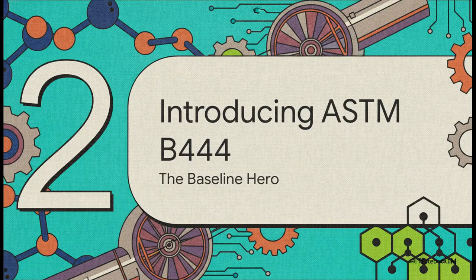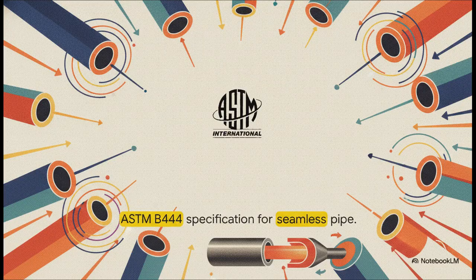Section 2. Introducing ASTM B444. This brings us to the baseline material that engineers turn to for these exact, unforgiving scenarios. The official ASTM International designation governs seamless pipe and tube, and that word, seamless, is absolutely critical here. It means the pipe is produced from solid billets by hot extrusion or piercing, and then it's followed by rolling and sizing. Because there's no longitudinal weld seam running down the pipe, the full wall thickness carries the pressure. Plus, there's no heat-affected zone from welding that could act as a weak point or a sneaky path for corrosion. It's built from the ground up for maximum reliability.